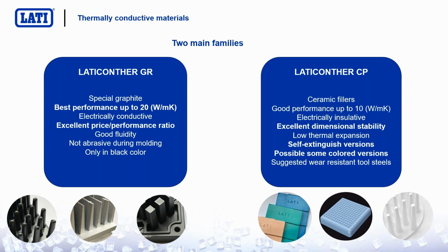Whereas the ceramic versions have also a good thermal performance, but are electrically insulative, so they can be used in applications where electrical insulation has to be guaranteed. Plus, another advantage of this family is that it can be colored in some color shades, and some self-extinguishing flame retardant versions can be tailor-made.